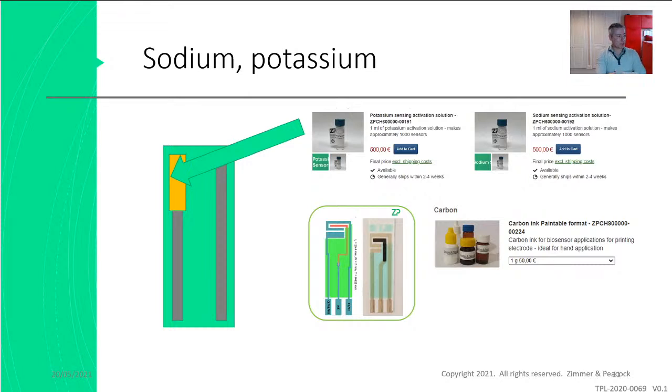So the question was, can we use the sodium potassium formulations on our gold electrode? I'm a bit concerned that you'll have a gold electrode and a silver chloride reference electrode. That means you might have a small low voltage battery set up, so you'll have a voltage that's not due to the sensing of potassium or sodium, but due to essentially these two dissimilar metals. We often use carbon in these electrodes, by the way. If you think you've got a problem because of the gold, then just hand paint some carbon on top of the gold pad, and that should fix your problems.